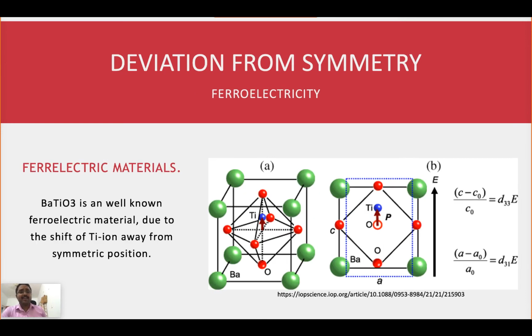Similarly, deviation from symmetry will give rise to ferroelectricity. You can see here, this is again a body centered cube where the titanium should be at the body centered position, but it is moved away. A small deviation is present. In that way we get electricity, because the amount of oxygen present near the titanium ion is more than in the bottom part.